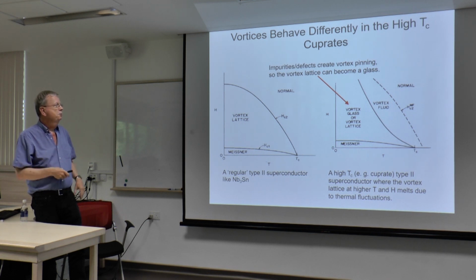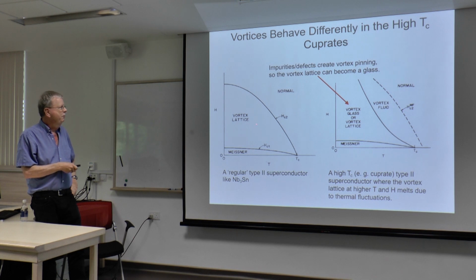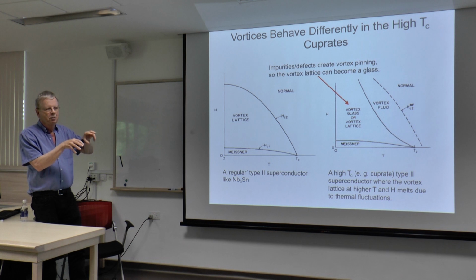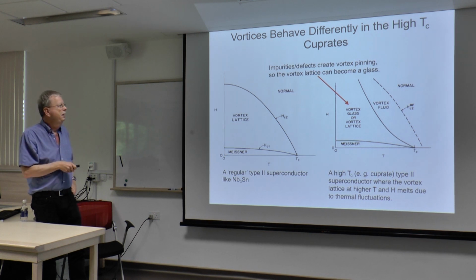Again, this is what we talked about for niobium 3 tin. It's normal. You cool through this phase transition line. This is a second order phase transition. And you get into a vortex lattice. Remember when I showed you for the cuprates, that's not a lattice structure, an ordered structure of vortices, that's a glass. But in a type 2 like niobium 3 tin, they're regularly arrayed, triangular, usually some equal spacing, vortex lattice, and down here, of course, is the Meissner-Ochsenfeld effect.